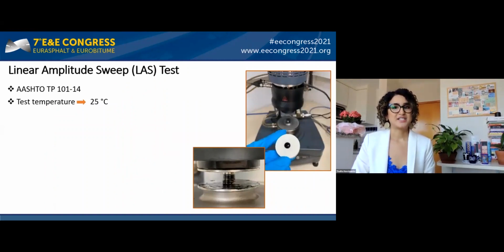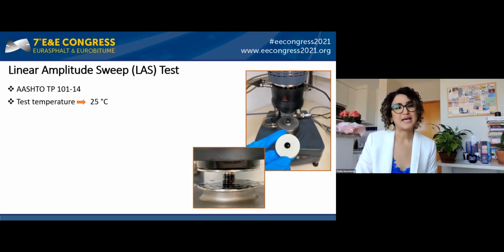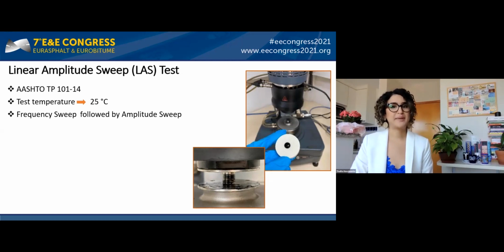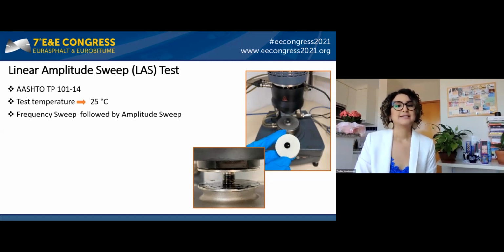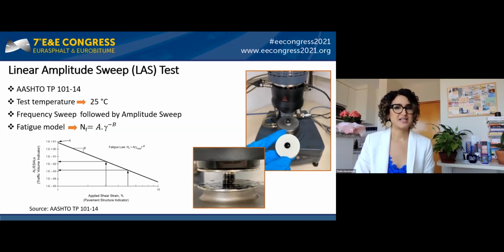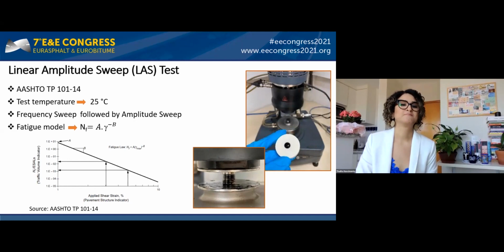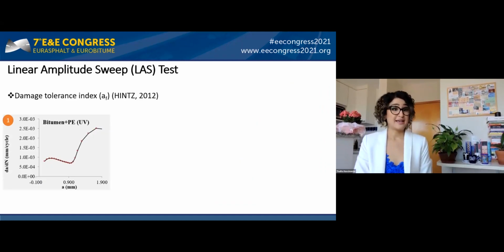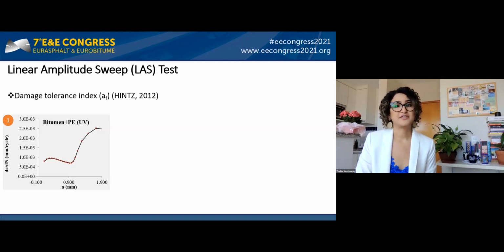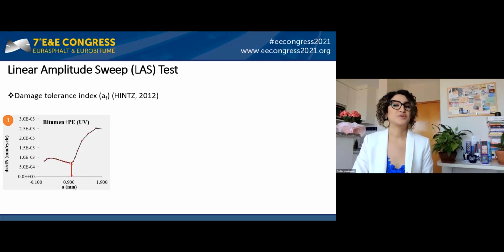Regarding the LAS test, it was performed in a DSR according to AASHTO TP 101-14 at the temperature of 25 degrees Celsius. The test was divided in 2 steps, a frequency sweep and an amplitude sweep, and the results were used to adjust the fatigue model, where Nf is the number of cycles to failure. The LAS results were also used to obtain the fatigue damage tolerance index, Af, related to material failure, which was proposed by Hintz in 2012.